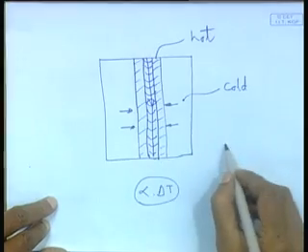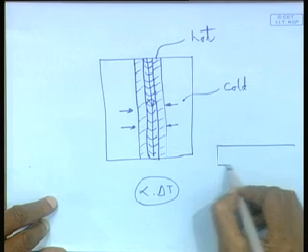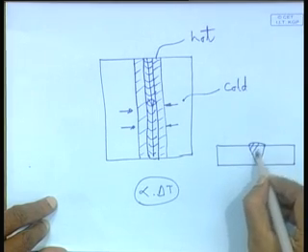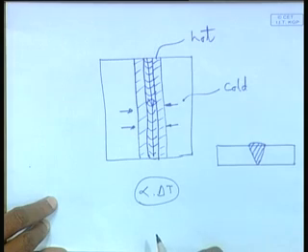So what you see is non-uniform expansion and contraction, which leads to the deformation due to welding, and welding being a process which involves localized heating. That means the entire structure is not being uniformly heated. It's getting heated up locally, and also the heating pattern is different. Different means the heating pattern at the top, when two plates are being welded. So your weld bead and the fusion zone would look like this.